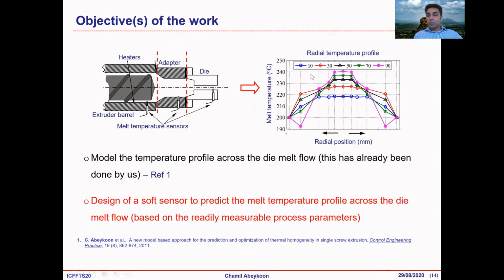So these are the measurements that we made, some experimental measurements. These are the measurements made for one of the dies, which is 38 millimeters in diameter, at different speeds. You could see at 10 RPM, we set the temperature to be 200 degrees at this location at the die. But you know what will happen at 10 RPM now? The middle of the melt flow is going up to 218, while this is going to now 200.